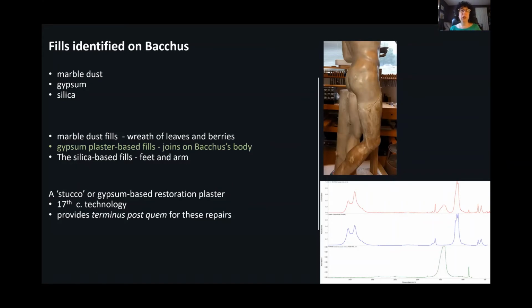But those weren't the only fills that we identified on Bacchus. We were also able to see gypsum fills or plaster-based fills, and those were predominantly on Bacchus's body in the area, for example, of the leg joints here, and then silica-based fills in the feet and arm. These gypsum-based restoration plasters, and I'm showing the data for that here, are really a 17th century technology. So that gives us an idea of the date after which these fills were applied.